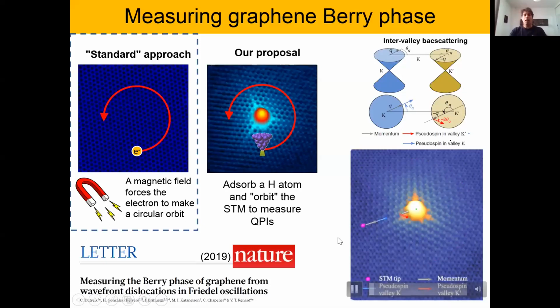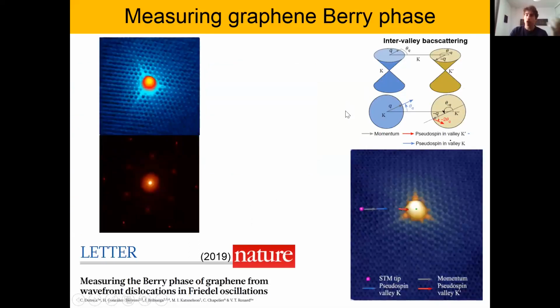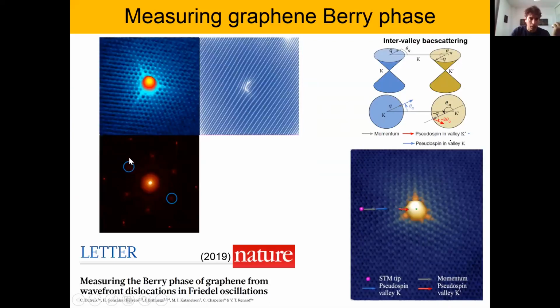So how do we do this in practice, how do we analyze just these inter-valley backscattering processes? With the Fourier transform, as I was showing you at the beginning. That's the STM image of our defect, and that's the Fourier transform. Now if we want to check just inter-valley scattering processes, we have to look at these high symmetry points where the root 3 is. And then if we make a pass filter of just this region, that's what we obtain.